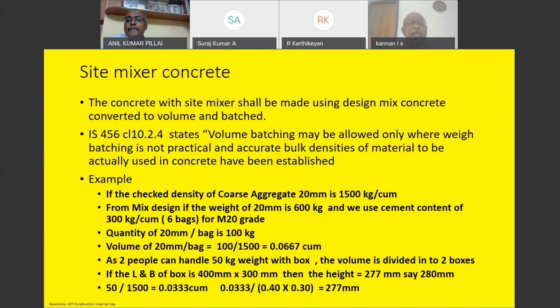Say, for instance, I have given an example. If you check the density of coarse aggregate is 1500 kg per cubic meter, let me assume that. Suppose you are using 300 kg of cement, that is 6 bags, and your 20 mm aggregate is 600 kg as per the design mix. That means per bag will be 100 kg of aggregate. So 100 kg of aggregate cannot be handled by 2 people, so you divide it into 50 kg boxes.